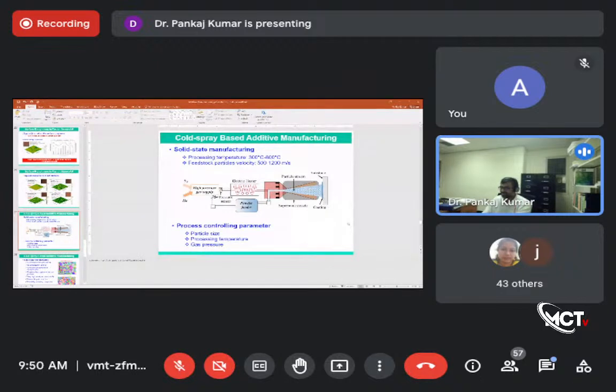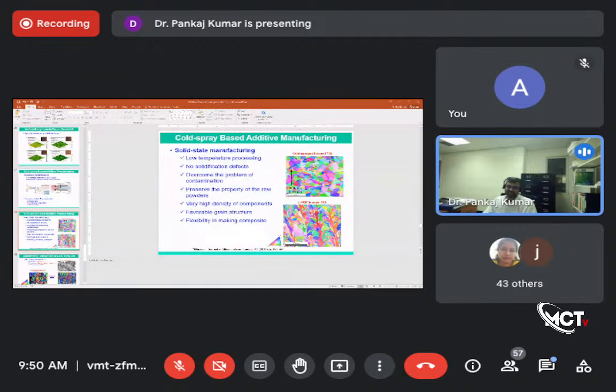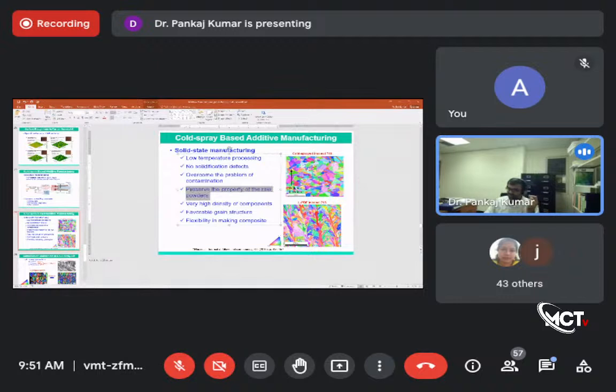But what is the advantage of this process? Why are people looking at it? Low temperature processing, no solidification defects like in fusion based techniques, and limited contamination. Most important is that the powder characteristics don't change because the powder didn't melt. So you start with an equiaxed grain structure in the particles. The density is very high. The grain structure is very good, right?